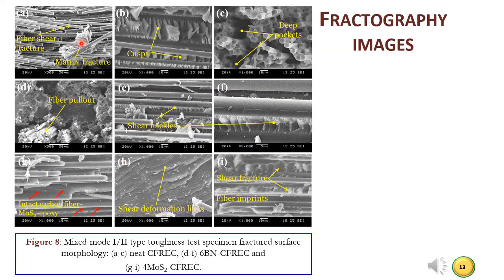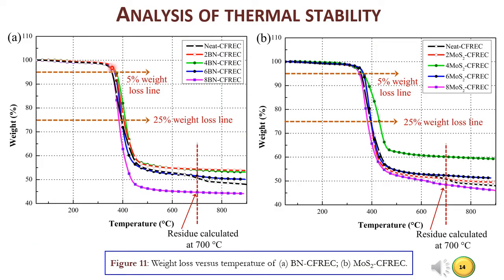Matrix fracture, fiber shear fracture and shallow cusps in neat CFREC reveal contribution of mode 2 load. Fiber pullout in 6BN CFREC indicates crack inability to propagate in tough hBN dispersed epoxy. Hackle pattern indicates violent stage of fracture and thus 6BN CFREC represents a tough composite. Intact carbon fiber in MoS2 dispersed epoxy is responsible for better toughness of 4 MoS2 CFREC.